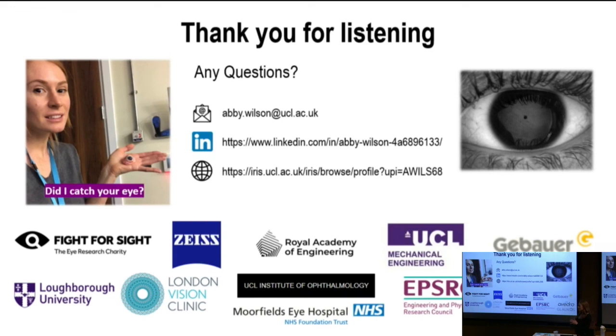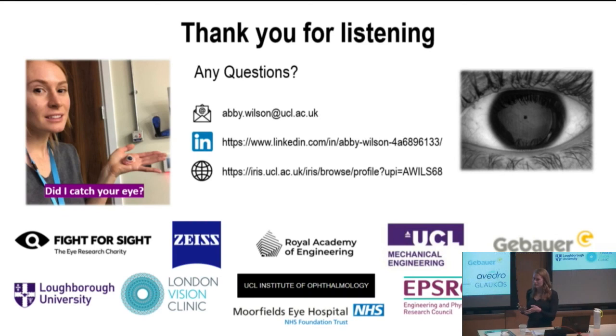There's been follow-ups for up to 20 years now, I think, and the cross-linking effects do last. The stiffness increase does last. It's also something where there is potential for follow-up treatments. It depends. The collagen only will have so many cross-linking sites, so there'll be a point where you cross-link it more and nothing would happen. Nothing would increase in stiffness. But say you did a conservative treatment where you increase the stiffness a small amount, there's potential that you could then do a further treatment later down the line.